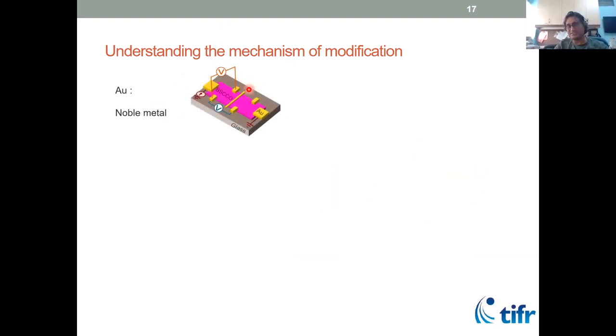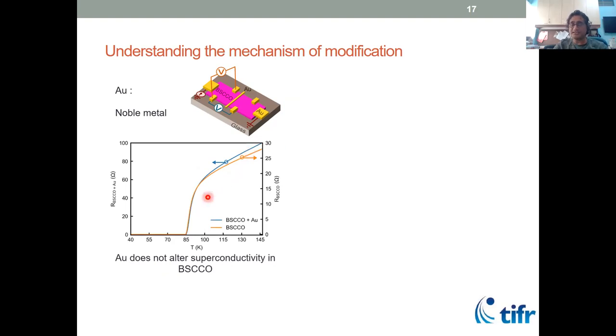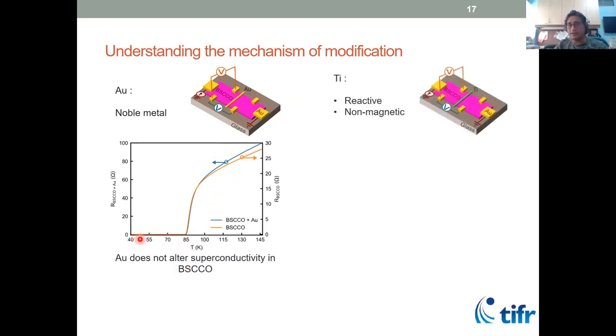And to understand this, we did several other experiments. So we deposited just gold, which is chemically inert, and we see that nothing happens to the superconductivity. It just remains robust. And to understand the specificity of different systems, we try to deposit some other material system to understand what's going on. So if you deposit titanium, then